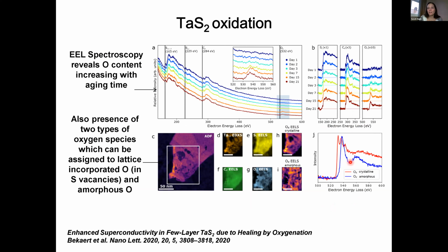So no, we haven't tried to. All we've done really is to have a look at these 2 different shapes, which we can extract out, and when you compare with lots of different crystalline structures in the literature, that's what you'd expect for a crystalline as opposed to the oxygen amorphous edge.